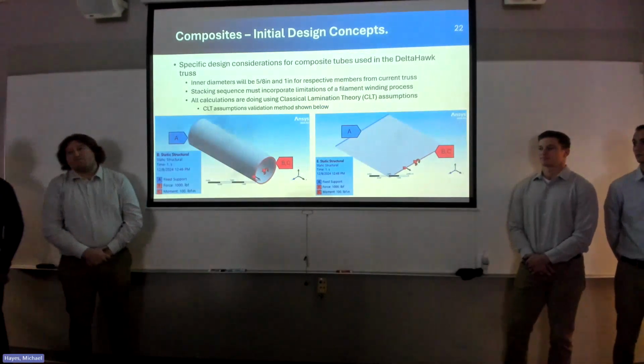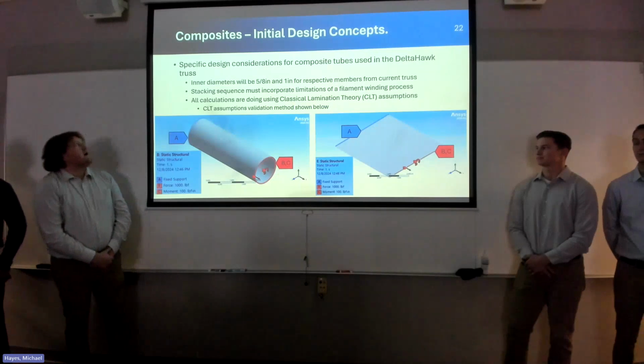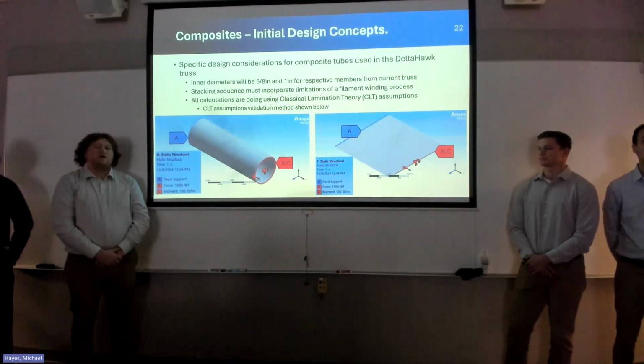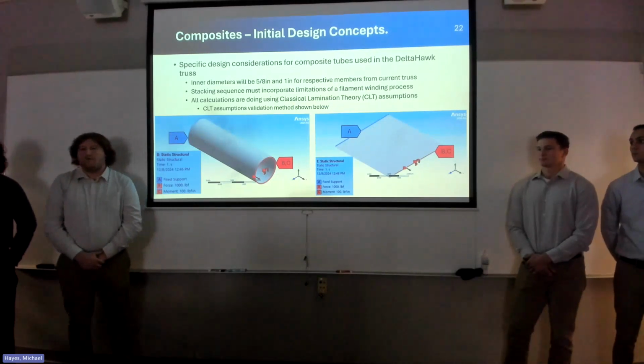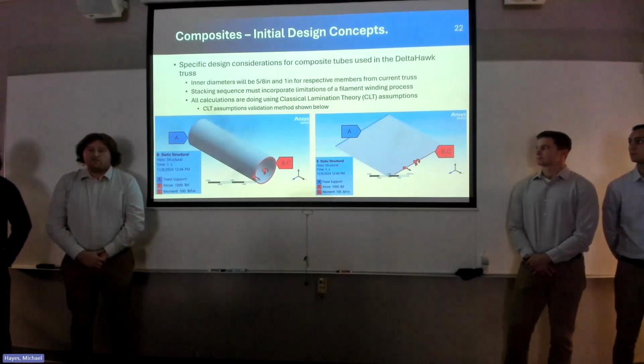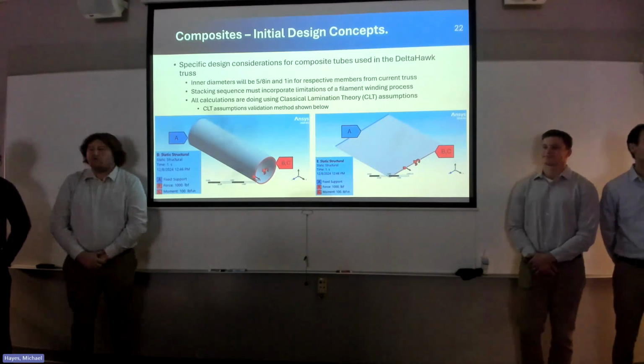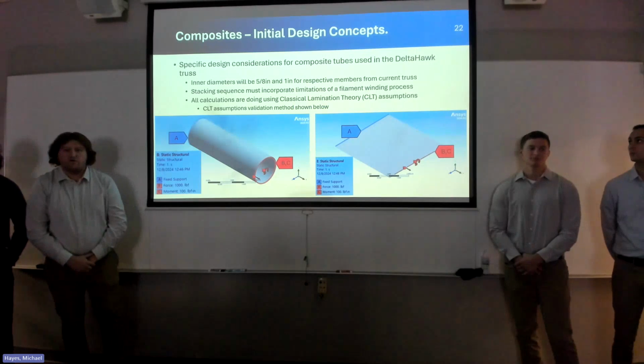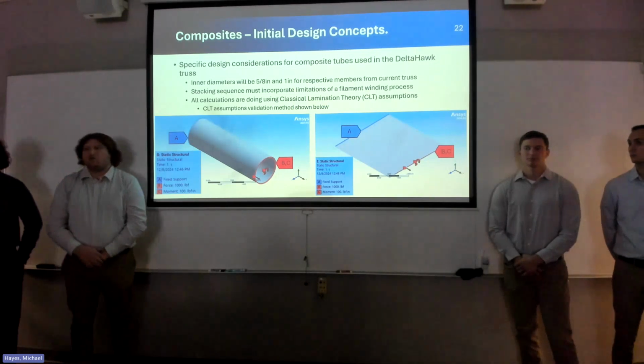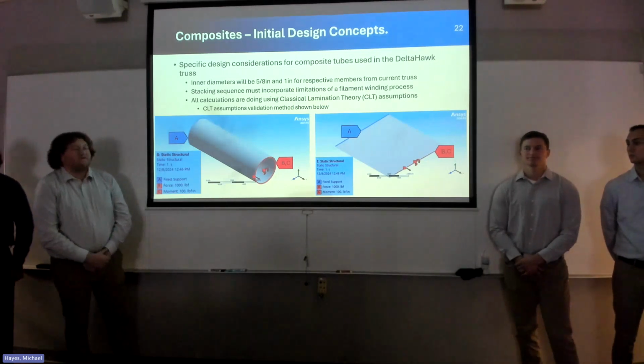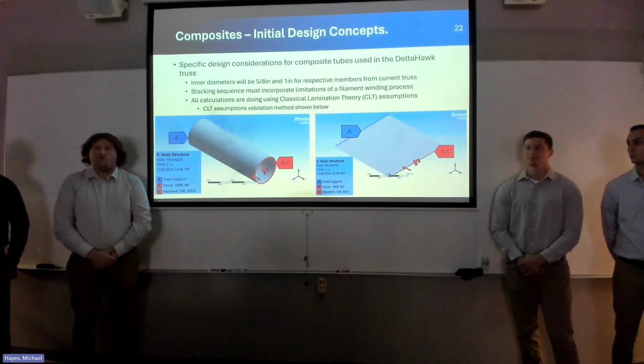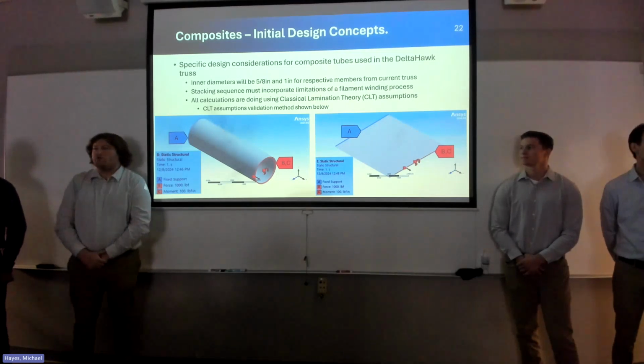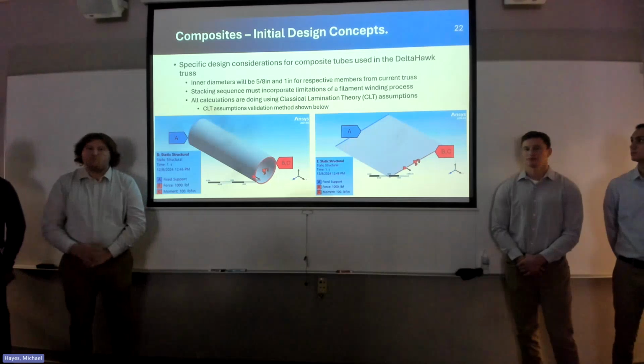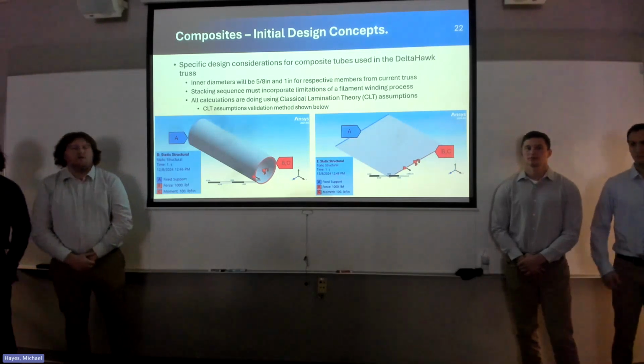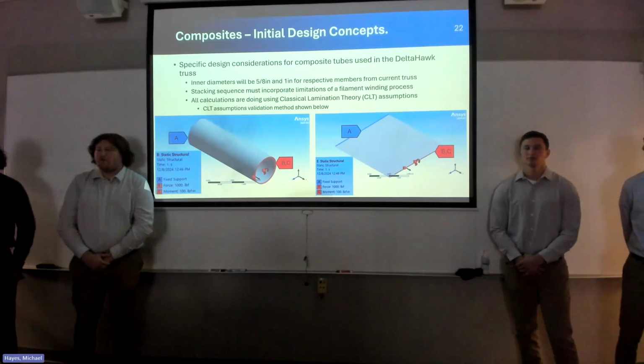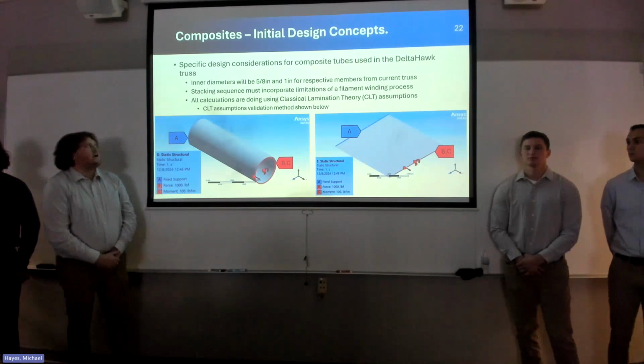Some initial design concepts I had to take into account for the composite tubes: on the current Delta Hawk truss, the members either have an internal diameter of 5/8 inch or 1 inch. As we transition to composite tubes, those inner diameters will remain the same for the respective members. So the 5/8 inch will remain 5/8 inch and the 1 inch will remain 1 inch. The stacking sequences that I test and downselect to must incorporate those limitations of filament winding. So again, that's the plus or minus alternating stacking sequence, as well as incorporating the plus or minus 30 to plus or minus 60 degree wind angles.